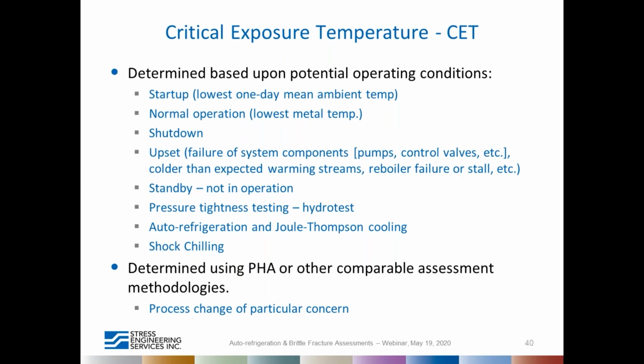So critical exposure temperature, this is very essential to determine accurately. It is determined based on startup, which can be lowest one-day mean ambient temperature, normal operation temperature, shutdown, or any other upsets, or standby when not in operation. And it can be from hydro test as well, and also auto-refrigeration and other Joule-Thomson cooling mechanisms. Shock chilling is another one when you introduce cold fluid into the system to cool the system faster to restart. And these are determined using PHA, which is the process hazard analysis, or other comparable assessment methodologies.